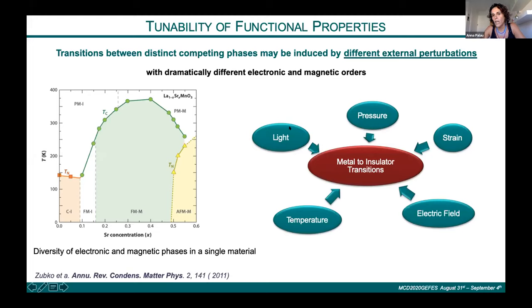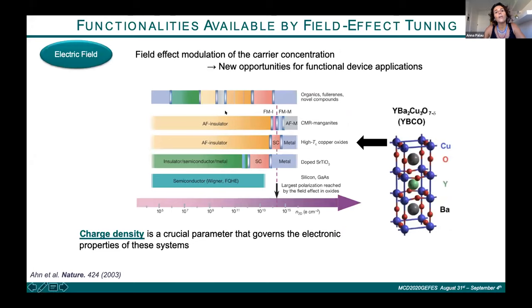For example, we can use light, pressure, strain, temperature, or, in the case that we are dealing with, the electric field, as the external perturbation that we use to try to induce these metal-insulator transitions. The electric field is able to change the carrier concentration in the material, and depending on the compound, this axis here shows the charge density of different materials. For example, in the manganites, we can obtain colossal magnetoresistance by doping the system.